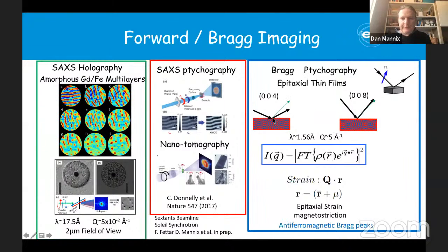is a way of looking at Bragg peaks. So these are looking at crystalline materials as opposed to amorphous ones, which are of technological relevance. You can also get other features. As I mentioned, you can get to the strain, and strain can arise from the epitaxial crystalline structure or even magnetostriction. In principle, you might be able to extend this to antiferromagnetic Bragg peaks and antiferromagnetic materials, which haven't really been possible with these methodologies so well. So it can go a little bit beyond what has already been done.